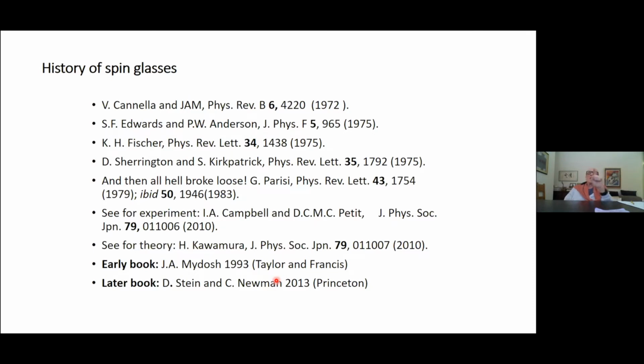We were lucky we got it into the abstract, and we worked on it by showing with a susceptibility measurement that there was a sharp phase transition. It was field dependent, concentration dependent, temperature dependent. A few years later, Edwards and Anderson came along with their theory, the first attempt to show that there is a phase transition in the spin glass in a complex magnetic system. And this was then improved by K.H. Fischer the same year.